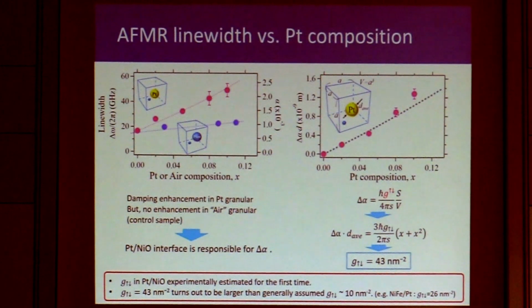This result, I think, is the first experimental result characterizing this mixing conductance by using a terahertz spin pumping experiment. And this 43 actually turned out to be a bit larger than the generally assumed value for the ferromagnetic platinum case and also the theoretically assumed mixing conductance.